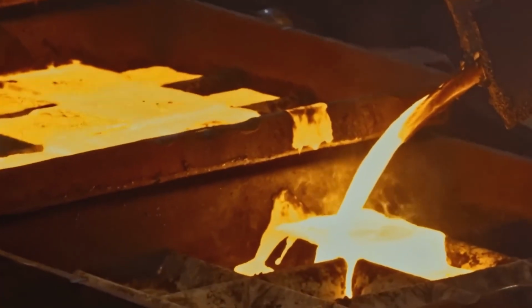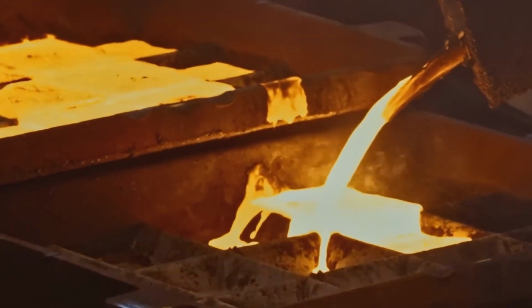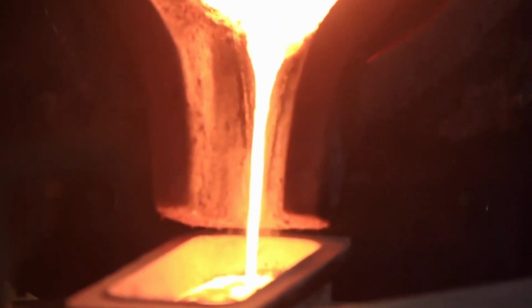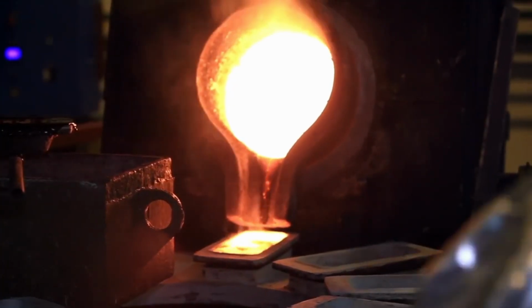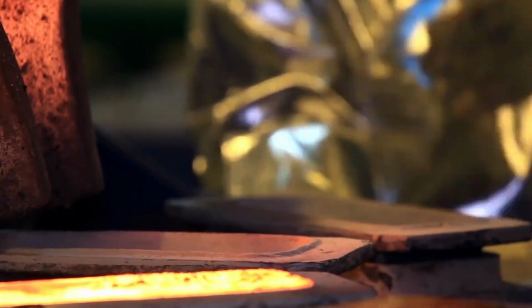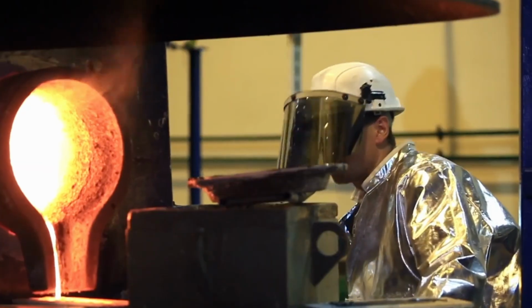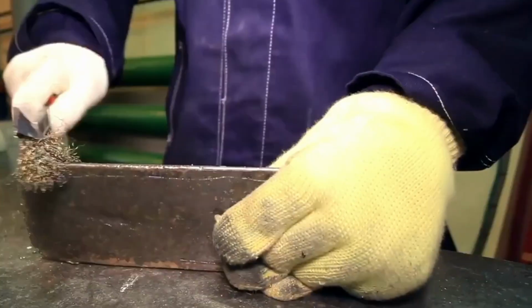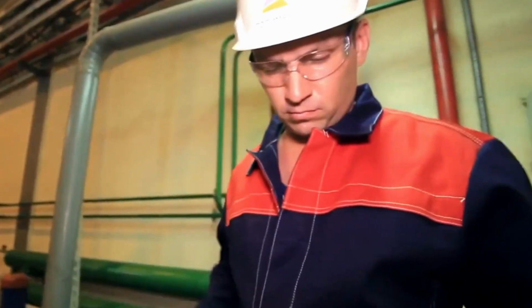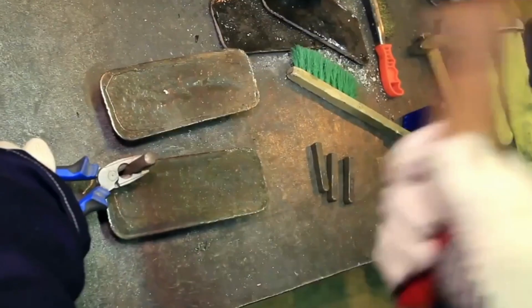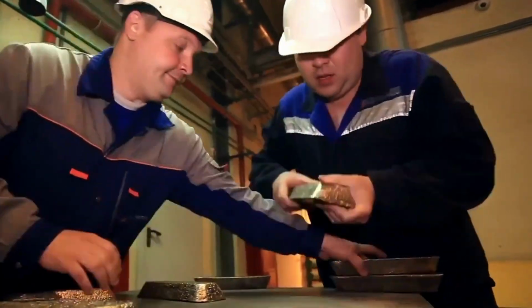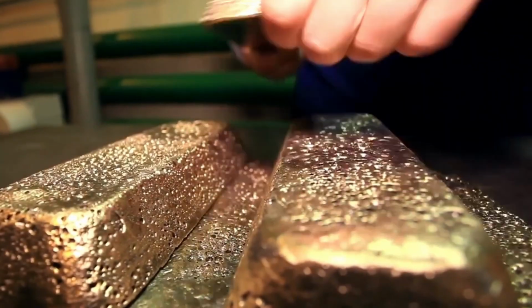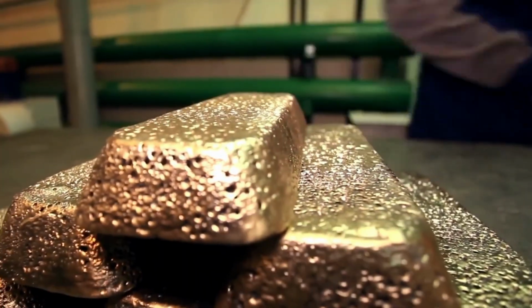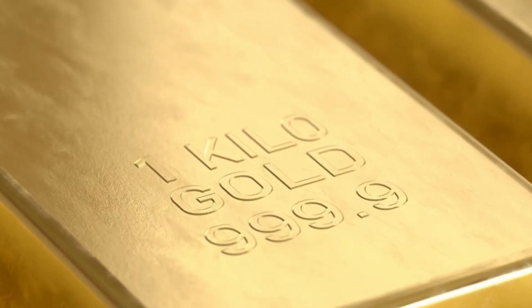Once everything's mixed, the batch goes into a furnace built to handle the heat, over 1600 degrees Celsius or 2912 degrees Fahrenheit. The furnace slowly turns so every speck of concentrate meets the full force of that heat. Missed spots mean lost gold. Inside, the gold and impurities melt, and something critical happens. Everything separates by density. Gold, being much heavier, sinks to the bottom. The lighter impurities float up, forming a layer called slag.